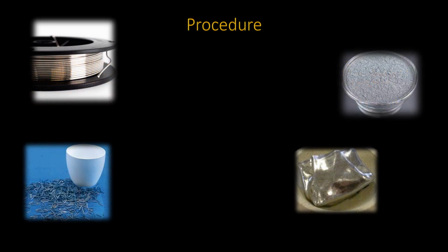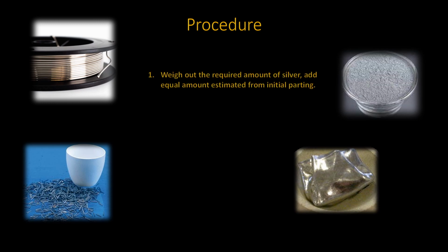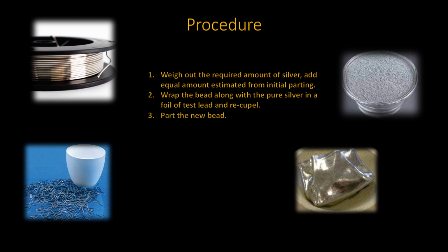Now that you know the ratio and have weighed out the appropriate amount of silver, take the bead and the silver and wrap it up in a suitable amount of silver-free test lead foil, as shown in the lower left of the slide. Then re-cupel. The new bead obtained will have, or should have, the right ratio of silver to gold. This new bead should part easily and completely.